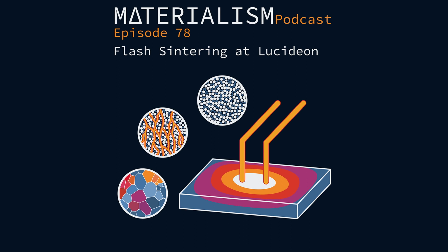Okay. Well, we just did an episode on thermal spray with GE. I don't know how familiar you are with it, but it's a very similar competing technology, and it has some differences. In thermal spray, essentially, you have a plasma, and you take whatever material you want to deposit and pass it through that jet of plasma. It's then melted, volatilized, and deposited onto the surface. So this is different because here you're sprinkling the powder, packing it onto the surface, painting it on, or dip coating it, and then I'm guessing you bring the plasma to the material that's already on the surface and melt it. So what's the difference in terms of microstructure and properties of these two different techniques?